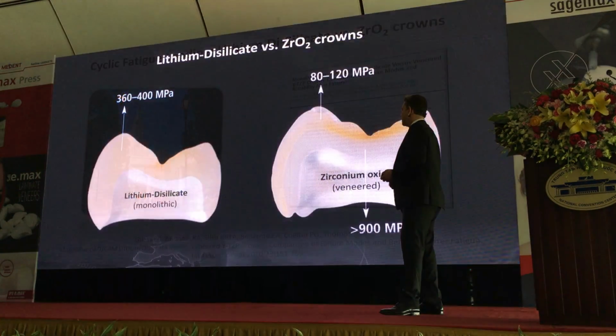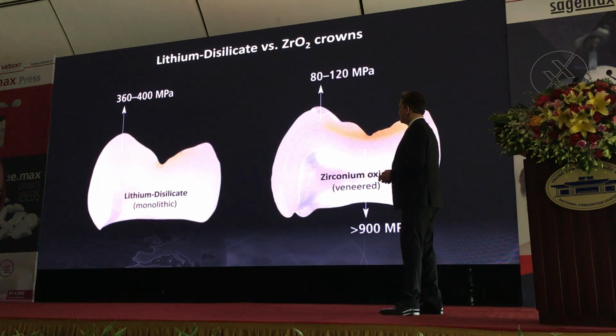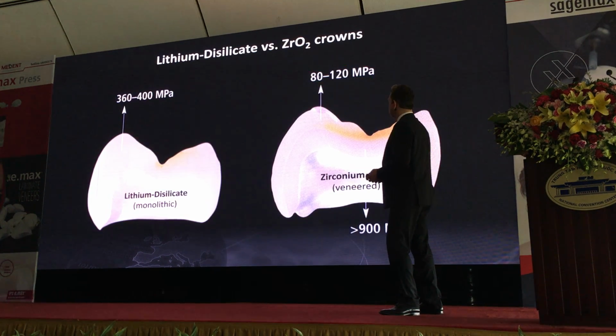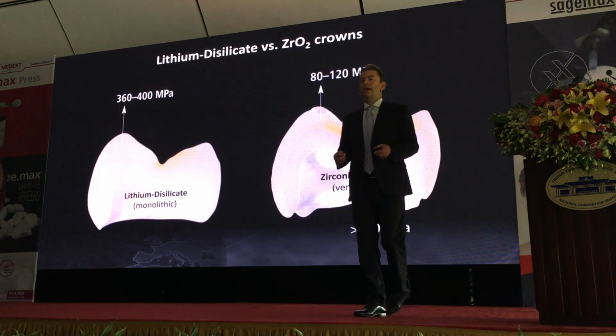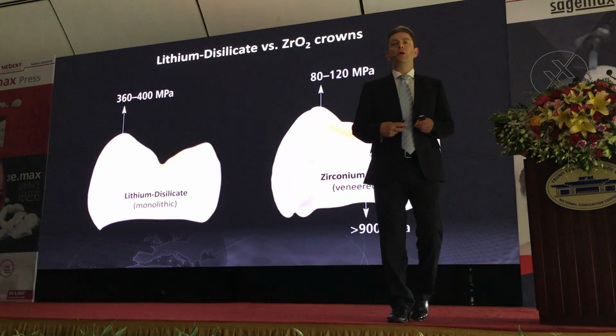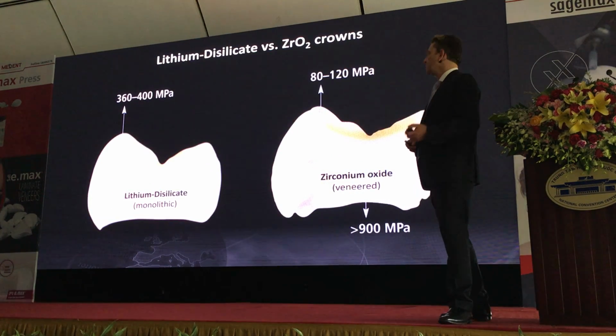Yeah. So for example, if you look at Emax here, monolithic means there is no layering on the top, and here is zirconium oxide. This is very strong, but the problem is when we do a layering on top of the zirconia, the veneering ceramic is very weak. So we are actually putting a weak material on top of a very strong material.